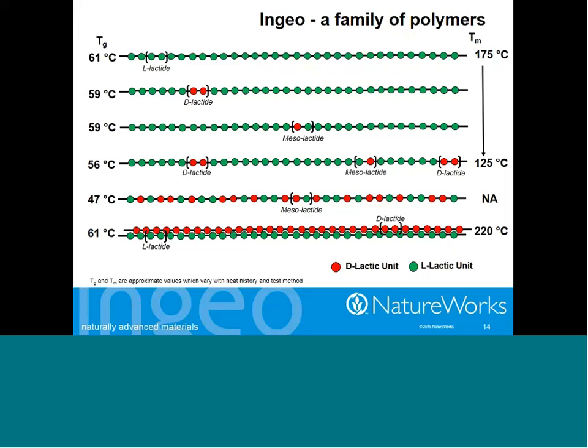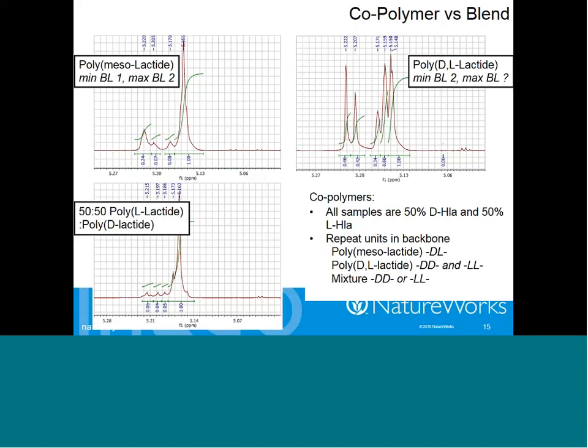And this phenomenon is often seen with racemic mixtures, which is what that polymer is. In fact, the melting point of racemic lactide is about 125 degrees, which is up from the 96-degree melting point of either L or D lactide. Most racemic mixtures do have a melting point that's higher than either purified enantiomer. So this is not necessarily unique to lactide or PLA, but it is sometimes useful.